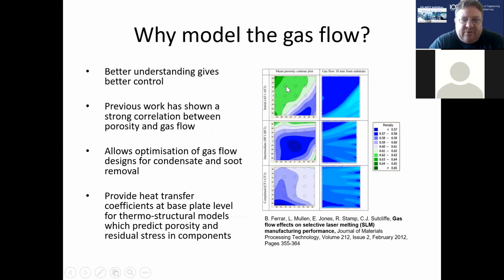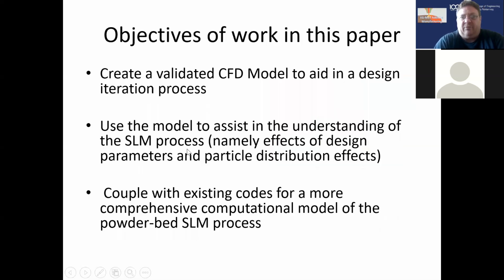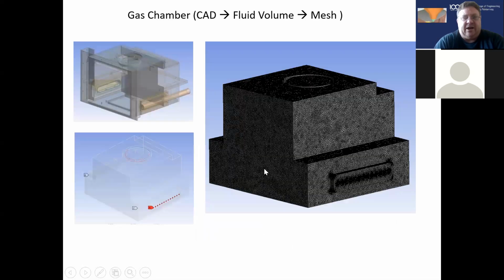So the little round circles here represent little cylinders for mechanical testing, and also to measure the porosity. And you can see the areas of higher porosity match the areas of lower gas flow, I should say, because it's argon. And so from that point onwards, they decided to use computational fluid dynamics to understand and then optimize the nozzles. And this is part of the work that is ongoing, part of Dan's work.